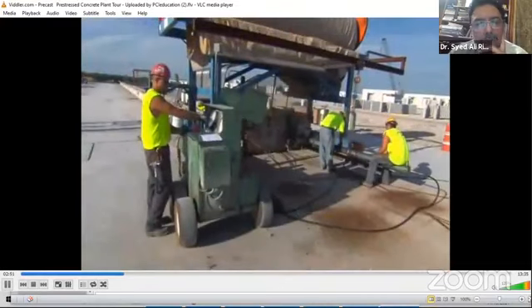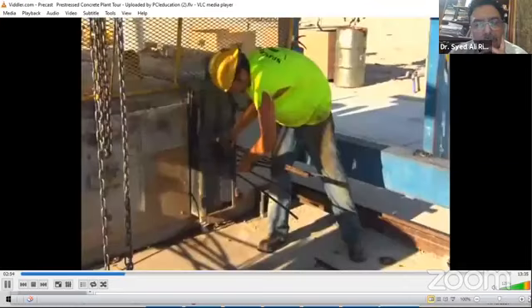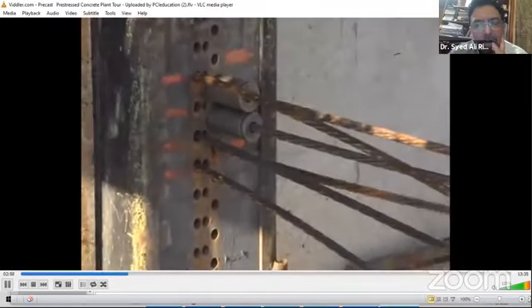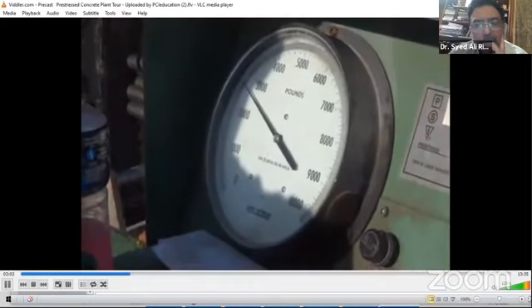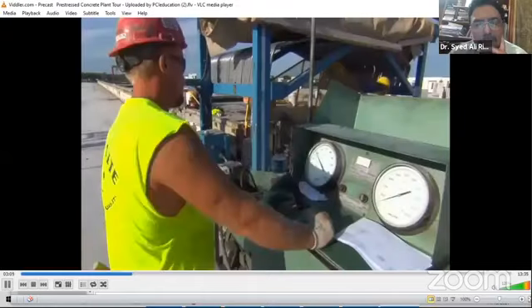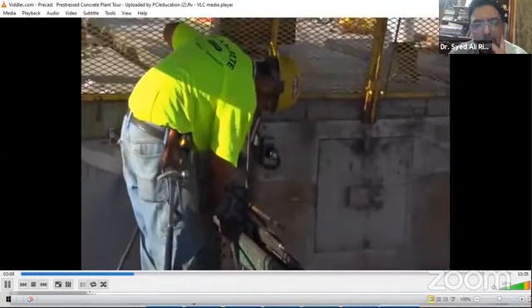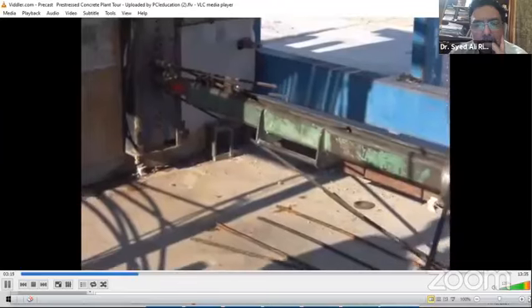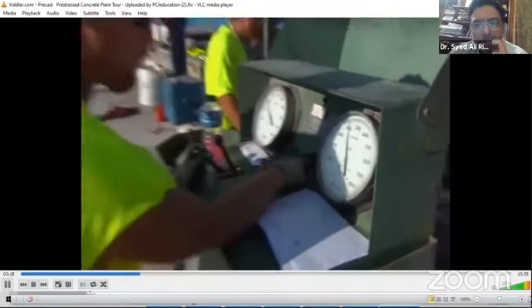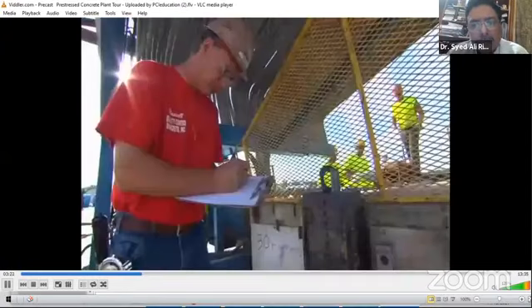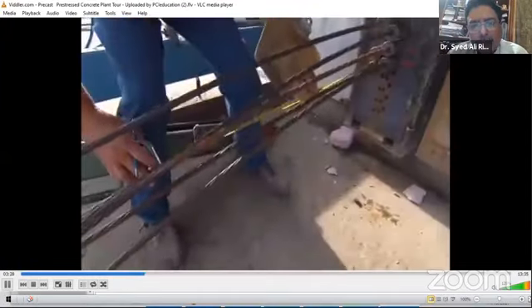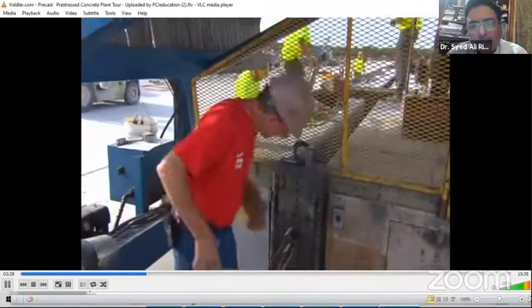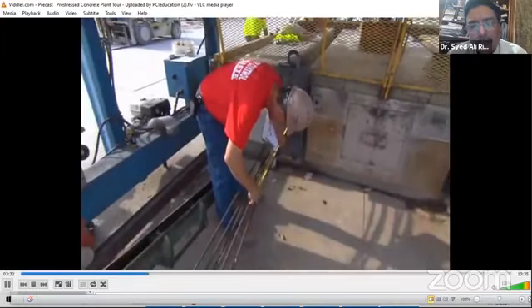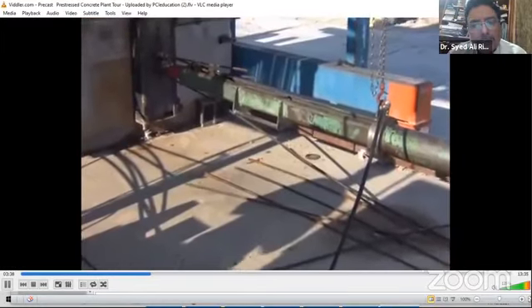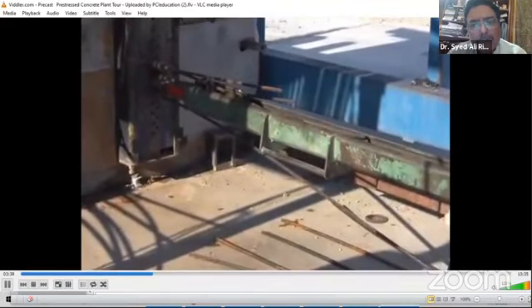The next step is the tensioning of the strands. In this case, we have straight strands, 6 strands at each stem, as shown here. The strands are first tensioned to about 2 to 5 kips based on the gauge pressure reading. A mark is made on the strand after the preload is applied. The strand is then tensioned to the specified level and is measured using gauge pressure on the hydraulic pump. The QC technician then checks the elongation against the theoretical elongation. The requirement is that the force on the gauge and the elongation must match within 5%. If that tolerance is not achieved, the reason must be established, and the strand may have to be detensioned and retensioned.